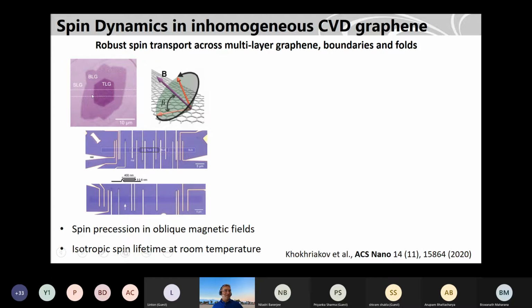So we wanted to see how spin transport takes place across these heterostructures. Also, in some graphene you see ripple-like structures here, and here there are some folds. When you transfer the graphene, it is first grown on a copper foil and then transferred onto a silicon oxide substrate to make these devices. While doing the transfer, you get lots of folds and ripples. Here, for example, we have a graphene with a fold around 0.6 nanometer in height and around 400 nanometers wide. We wanted to see how spin transport takes place across this structure, and also in a device where the ferromagnet is situated between these bilayer, trilayer, and single layer structures.